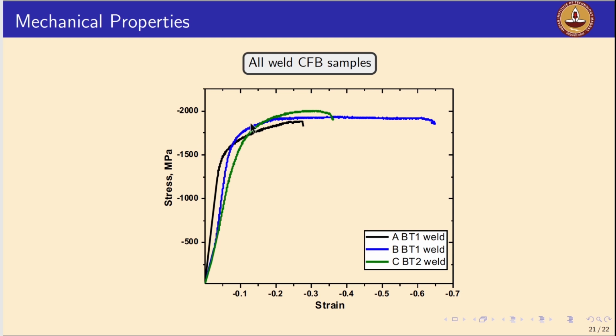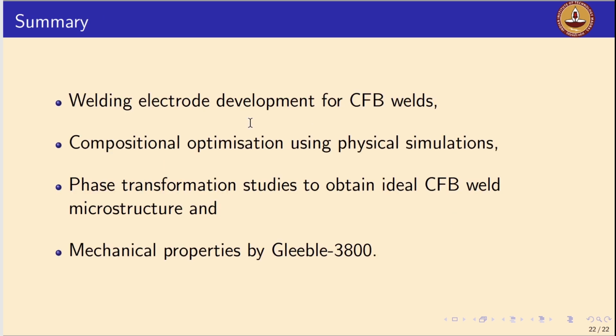So we optimized the chemistries, and we avoided hot cracking, and we also optimized the interpass temperatures as well as the isothermal bainitic holding time and temperatures to achieve the mechanical properties in the weld, which is even better than the actual base material, right? So this gives an idea about the use of Gleeble for optimizing welding electrodes, especially in the complex phase bainitic steels, right?